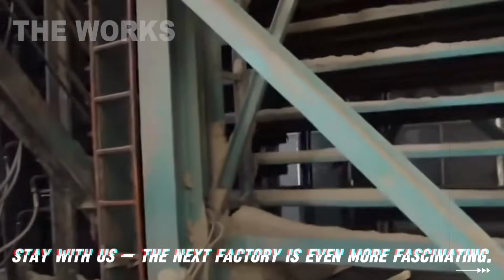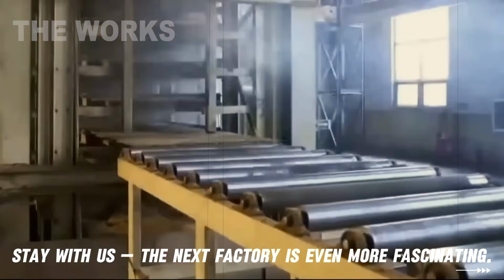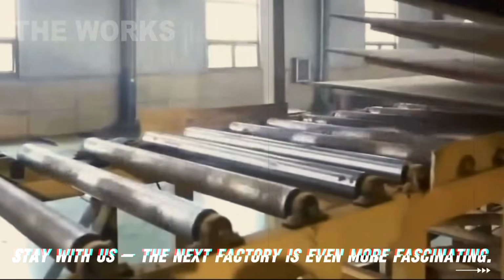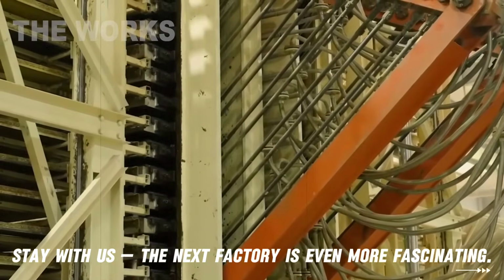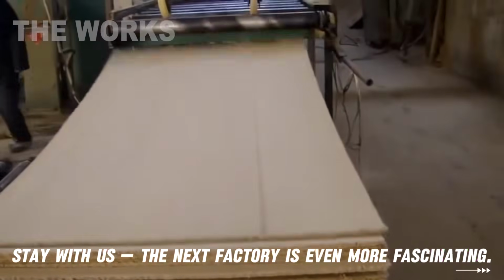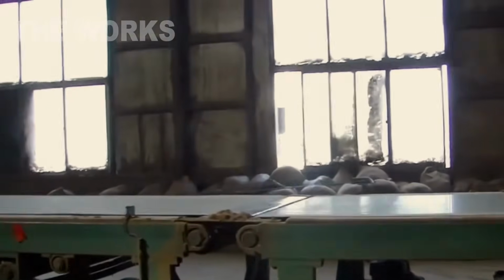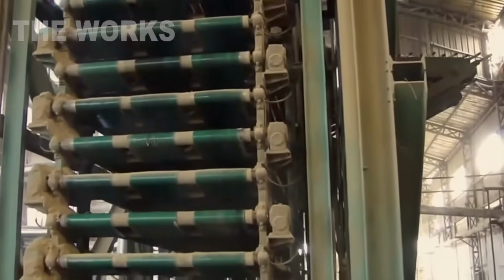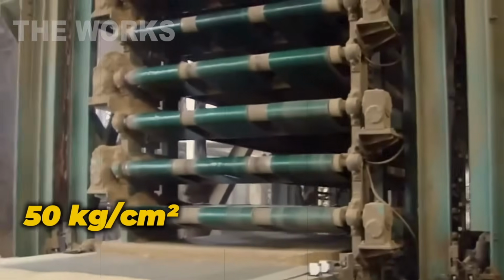Second, high temperature, 400 degrees Fahrenheit. This heat does two things. It activates the resin, causing it to polymerize and bond the fibers into a single monolith, and simultaneously evaporates any remaining moisture, which escapes from the board as hissing steam. After just a few minutes in this steel embrace, the loose mat transforms into a solid, dense, perfectly flat, and still very hot MDF board. Pressure in modern presses can reach 700 pounds per square inch. Imagine an adult cow standing on an area the size of a postage stamp.